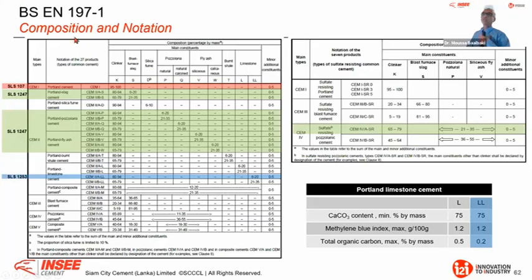But according to the EN, this cement is part of the CEM II. And we produce according to the LL in Sri Lanka. Our Sri Lankan standard does not have the B, therefore up to 35%, and we don't have the L class. We have only the LL. Now, this is from the composition. Just to see where we stand compared to the European, we still miss Portland composite, slag cement, some of the pozzolanic, and also some of the CEM V.